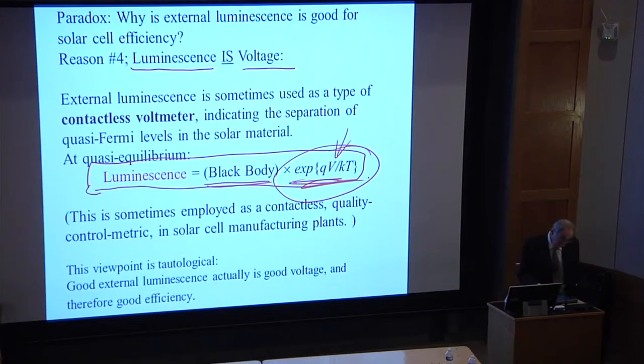But to give an idea of what's going on, people in the know will not bother with a voltmeter. They will just measure the luminescence. If you calibrate the luminescence carefully, and I've managed to convert everyone at Berkeley to do this, they don't do IV measurements anymore. They do light in, light out measurements. And if you calibrate it, it's a contactless voltmeter. And so this is a statement that, yes, of course you want more luminescence because luminescence measures voltage.